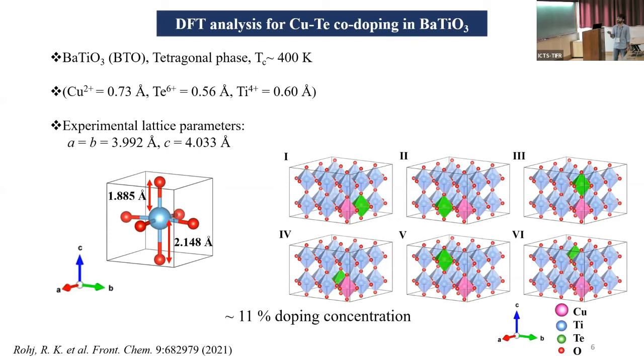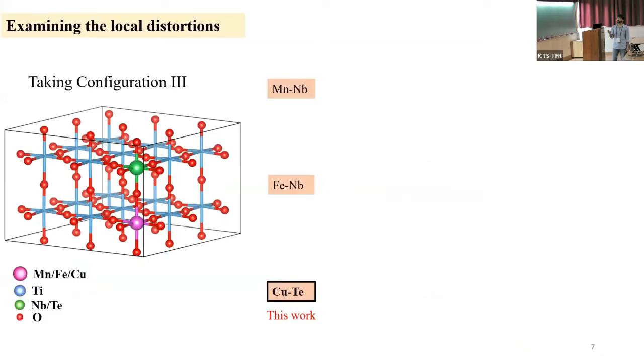and we replaced 2 titanium atoms, shown in blue over here, with 1 copper and 1 tellurium, copper shown in pink and tellurium in green. Now, since 2 titanium atoms have been replaced amongst 18 of them, it accounts to an 11% co-doping concentration of copper and tellurium. We individually relaxed all these supercell configurations and examined the local distortions in all of the configurations. Right now, I'm taking an example of configuration 3.